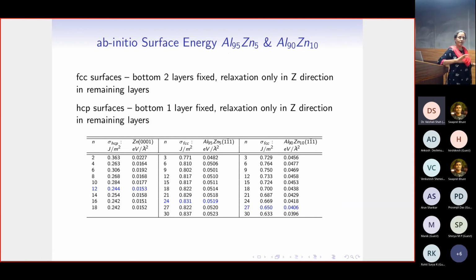So 600 is still doable with a decent amount of high performance computing infrastructure. We may be able to stretch it till 1200 at the most. But beyond that, it is going to be very difficult. It's just impossible to get any results within a reasonable amount of time. I have a limit. Which is why I put in all this considering that this is going to be for an audience which is not an expert in doing first principles calculations. It's an enormous calculation. That's the main problem.